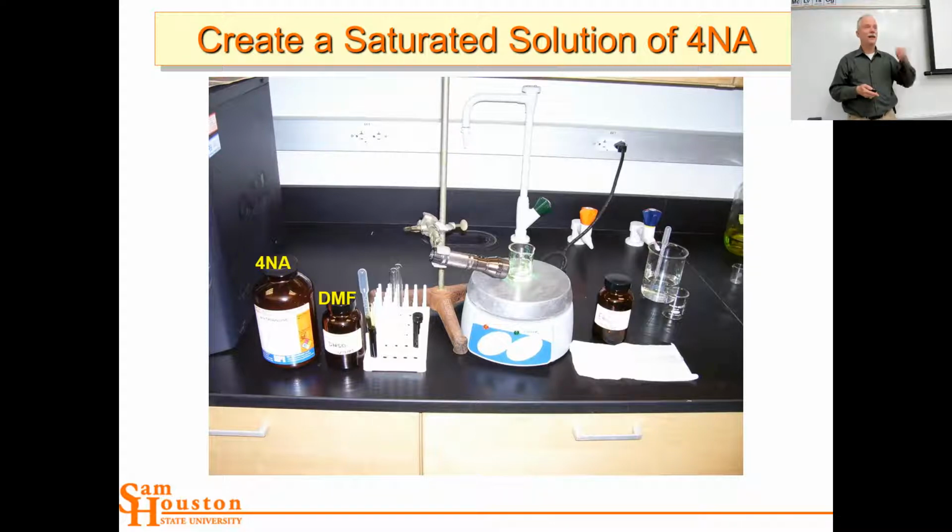That's really helpful if you have really slow precipitation and you want to keep it slow. So you can shine a laser through there and see if you're getting microcrystals. If they haven't settled yet, they may still scatter light. And you want to let them grow if you want to get some larger crystals. You don't want to agitate it. As long as you're not exciting your molecule with the laser? Well, that's true. That might be a potential issue, but most of the time it's just scattering off. But yeah, you're perturbing the system a little bit, but shaking it perturbs it even more.